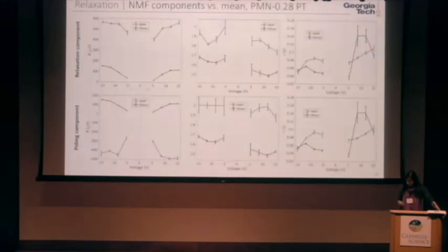One thing that is interesting that I want you to notice here is that if I had kept myself just to the mean value of all these 2,500 data points, which would have been the equivalent of making a macroscopic measurement, I would have got data that are extremely different from looking at the average of those. If I fit every single curve and look at what I find with respect to the components, I get, for example, betas for the poling that are almost strictly close to 1, and that are substantially larger than any of the mean values that I would have found.